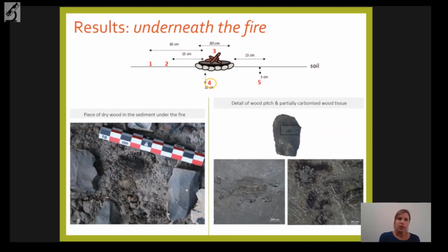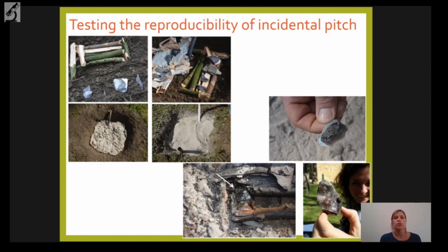Another interesting observation underneath the fire is the fact that the stone tool was positioned on a piece of wood, and this apparently resulted in the formation of wood pitch and partially carbonized wood tissue on a stone tool on which no such glue was put initially. This interesting result, of course, necessitated a follow-up experiment to test the reproducibility of such incidental pitch.